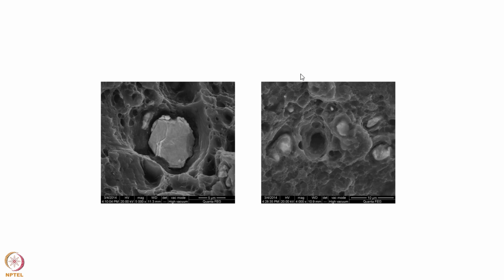You would see the same thing in a fiber reinforced composite also, depending on the nature of the interface bonding. If it is a strong interface, you would see a similar feature. Instead of a particle, you would see a broken fiber sitting here, and the other half of that broken fiber will be found if you look at another part of the fracture surface, okay? The corresponding region, if you see, the broken half can be seen on that part, okay? And if the interface bonding is weak, you will see a hole, the size of which will be similar to the size of the fiber or the diameter of the fiber. And that would indicate that the fiber was sitting over here, but due to a weak interface bonding, it has been pulled out when the composite was loaded, okay?